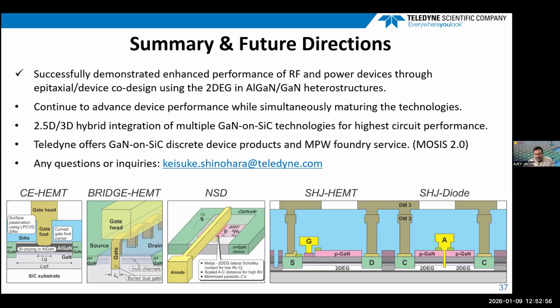Yes. The next question from Barry is, what is the mechanism of silicon doping in AlGaN mitigating the current collapse? I had the same question here. How do you do the silicon doping here, how precise is it, and what's the doping density? Yeah, silicon doping is done similarly to the way it is done in a conventional GaN HEMT. We just introduced the silicon doping in the aluminum gallium nitride layer, and it helps in terms of current collapse. It is known that there are traps at the interface of GaN and aluminum gallium nitride. By introducing silicon doping, we think that it passivates some of the interface traps, and that results in reduced current collapse.